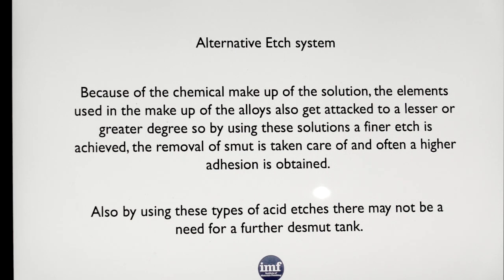So you get this differential attack because you've got different metals there. With caustic, as I said before, aluminium will always preferentially get attacked. Copper wouldn't get attacked. Iron, even below it, would get a degree, but not to the same extent. But if you use an etching system based on a fluoride, you tend to get attack of all the metals that are actually in the alloy, which is better, actually.